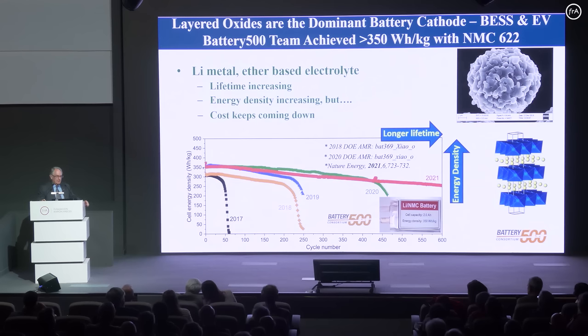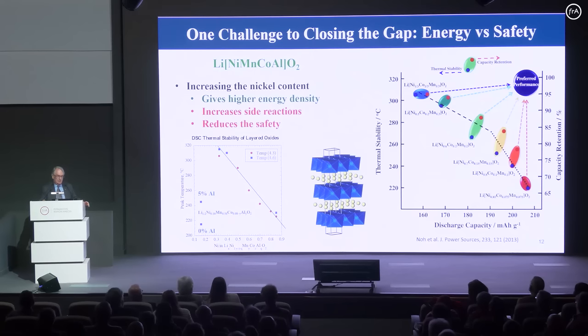These particular materials have what we call this meatball morphology. You can see it in the top right-hand side. The agglomerates are very small particles formed into these larger particles. So what we want to do to reduce the cost and increase the energy in the end is to put more nickel in these materials and less cobalt, but there's a big challenge there. Again, don't worry too much about the numbers, but you can see in the bottom right-hand side the nickel content. The higher the nickel content, the higher the capacity of the materials, but the less stable.